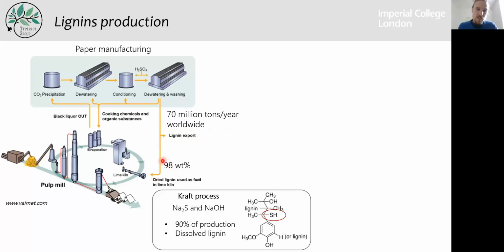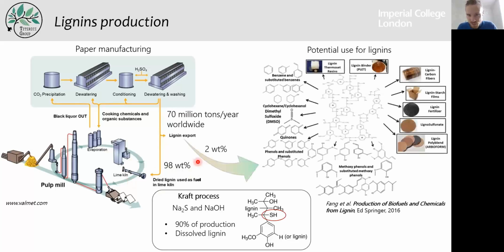And 98% of this is burned for heat recovery. With the remaining 2%, we're trying to find lots of applications because lignin is very functionalized and it's the only aromatic polymer that we can find in nature. So there are loads of potential applications as fuels. These fuels would probably cost a huge amount if we were trying to make them from fossil fuel. But it also finds applications in thermosets, adhesives, binders, lignin carbon fiber, which we will see today, and loads of other things. Interesting to note is that during the kraft process, these really harsh chemicals transform the structure of lignin by adding some sulfur groups into the structure.